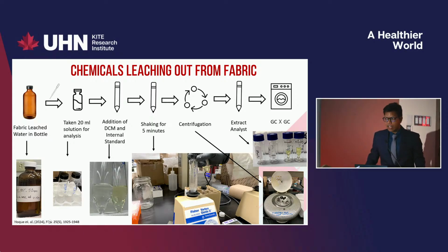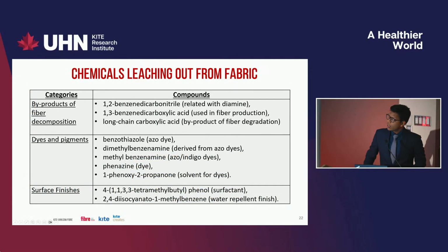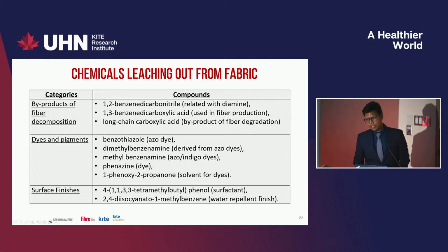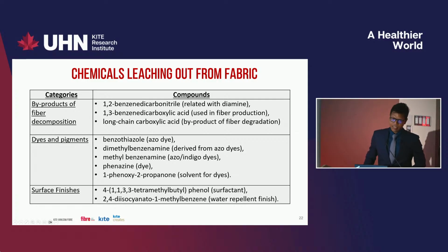So we studied 11 commercial fabrics which are made from different combinations of high performance fiber, which had particularly dyed and water repellent finish for its intended end use. So we did a very in-depth study. We took the leached water from the fabric. Then we analyzed the leached water with two-dimensional gas chromatography with TOF-MS and also with FID. And we figured out 276 chemicals, unique compounds. We identified 276 unique compounds from these 11 fabrics in combination.